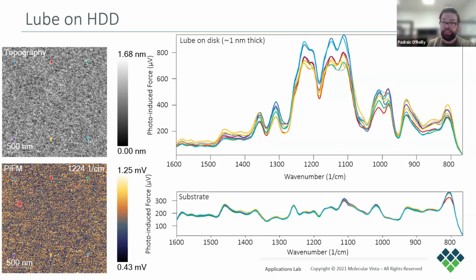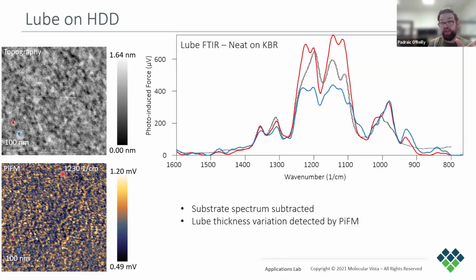And the PiFM image taken here in the bottom left corner is at a lube wave number. And it looks like there are nanoscale variations. It almost looks like noise, but when we zoom in, we see that they are real. So these are 500 nanometer wide images. And you can see the brighter and darker regions in this PiFM image.